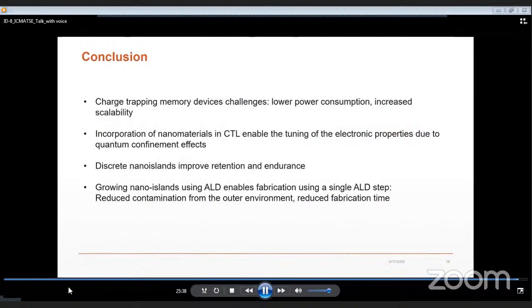We have also presented the growth of nanoislands using the ALD tool and explained the growth mechanism. Finally, we have shown that the ALD grown nanomaterials allow us to grow the active layers of the memory device in a single ALD step, thus reducing the contamination probability and reducing the fabrication time. With that, I would like to wrap up my talk, and thank you for listening.